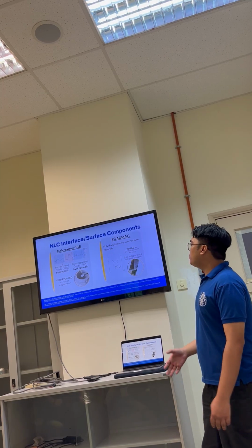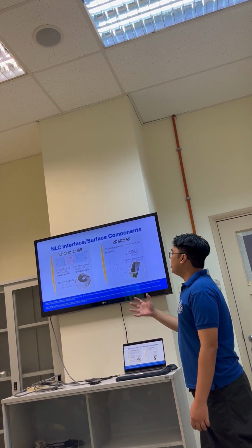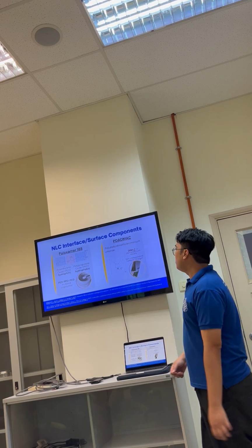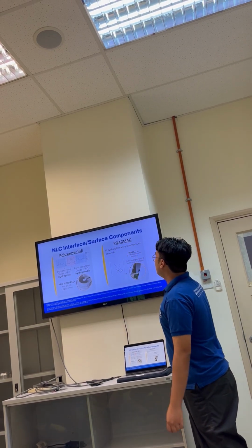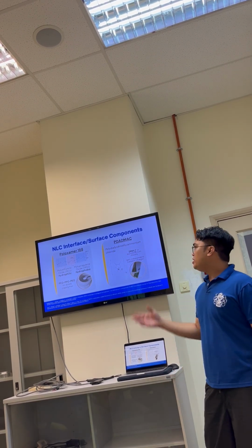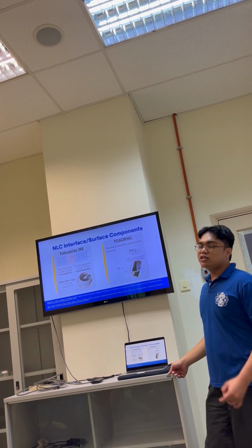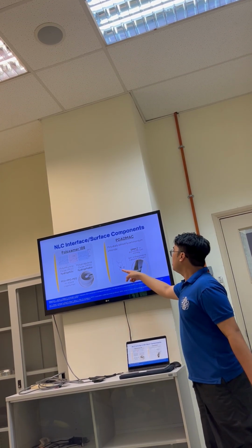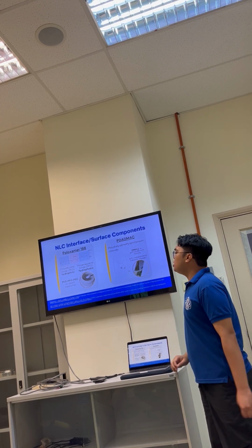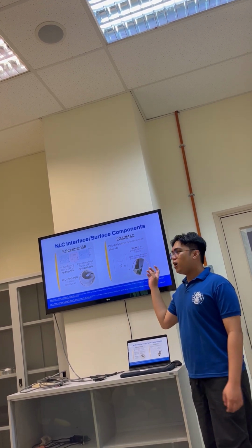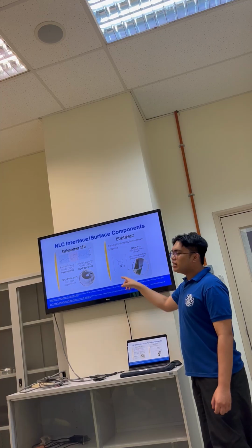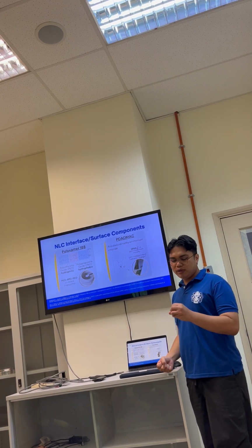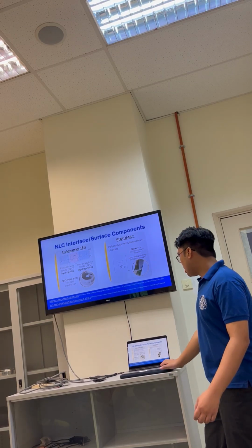Next, we have to surface modify our NLC system. I will explain more later why this would be relevant. But anyway, polydiallyldimethylammonium chloride, or PDADMAC, can be used as our surface modifier simply because of its positive charge in the pyrrolidinium moiety, which is pH independent. So we have this maintained pH-independent cationic charge regardless of where we place our nanoparticles in.